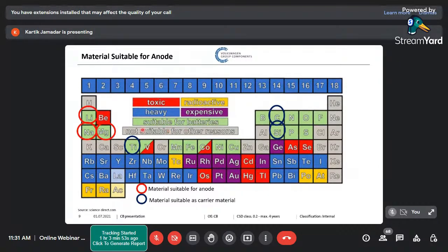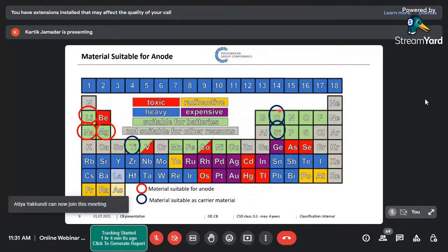And titanium is one of the materials which can be used instead of carbon. You know, titanium is a heavyweight material, so the weight will be higher and the energy density will be lower. But a very important thing is that these titanium batteries are very stable, very safe batteries, and they have practically no aging. They can live for years and years. But the only problem is it has only 2.2 volt. So it cannot give you 4.2 volt like carbon with lithium and those things. It can only give you 2.2 volt.